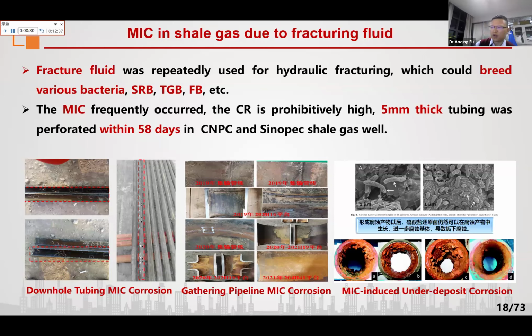Here, the MIC frequently occurred no matter in the gathering system or in the downhole system. Here you can see the picture very clearly shows how the corrosion occurred in those two systems. The corrosion rate is prohibitively high in both systems. Here I just give an example. The 5-millimeter thick tubing was perforated within 58 days, less than 2 months. There was a lot of perforation. The corrosion rate is very high.